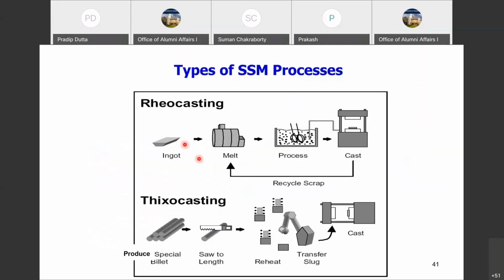So there are two methods. One is directly, you can have ingot, molten, and then processing, and then finally cast into the parts using this slurry. The other one is a thixocasting process, which is a more elaborate process, which we tried. That is, we first produced the billets having the non-dendritic microstructure. Therefore, what we needed was a DC casting facility with electromagnetic stirring. Then we cut those into certain sizes, reheat, not totally remelt, up to the semi-solid temperature, and then cast it into parts using a die casting machine. So this is the entire process that we not only modeled, but also did in our laboratory.